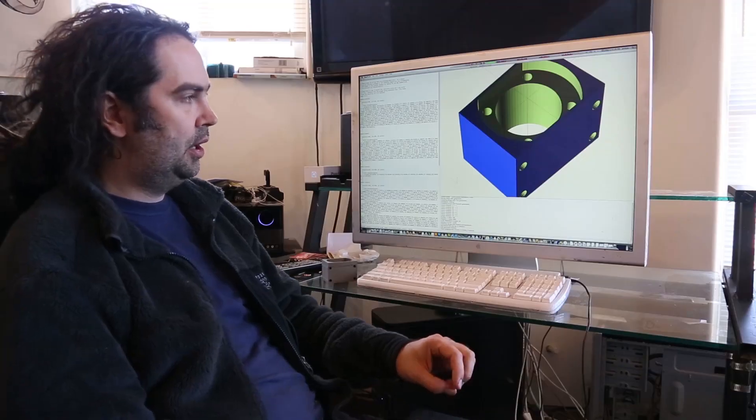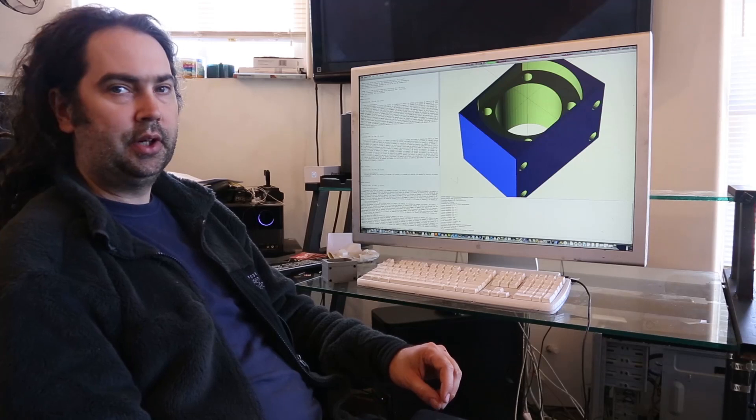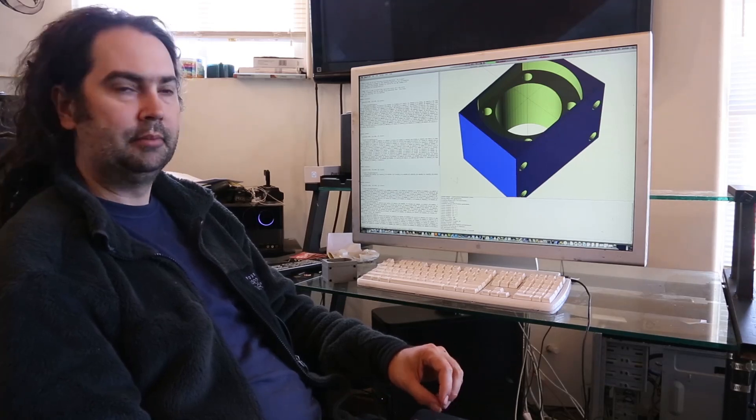When it fit perfectly the way I wanted, I printed it again at 103% to account for the shrinkage of the aluminum casting.